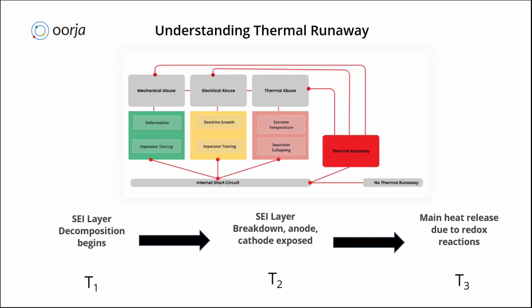And because of that, whenever you have very high lithium plating, it may also lead to dendrite growth, which will also lead to internal short circuiting. So there could be various reasons because of which thermal runaway may happen. And because of thermal runaway happening in a cell, it may also cause thermal runaway propagation in the pack itself.